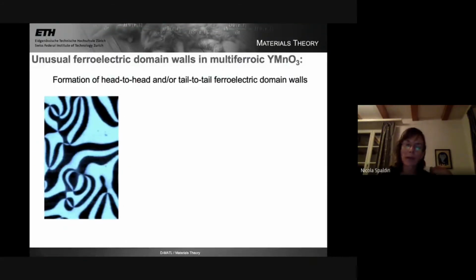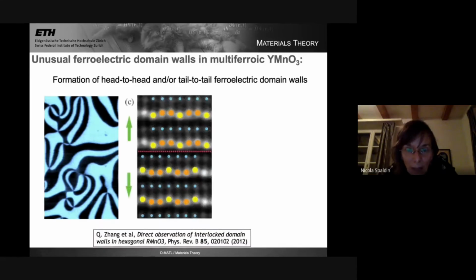And so I want to show you another of the useful aspects of these multiferroics. Here's just an extract of that ferroelectric domain structure again. And in this particular orientation, the white is representing electric polarization in the up direction, and the black is representing electric polarization in the down direction. I'm going to show you again a high-resolution microscopy image. This is not from my work, from the group of Zhang and co-workers.